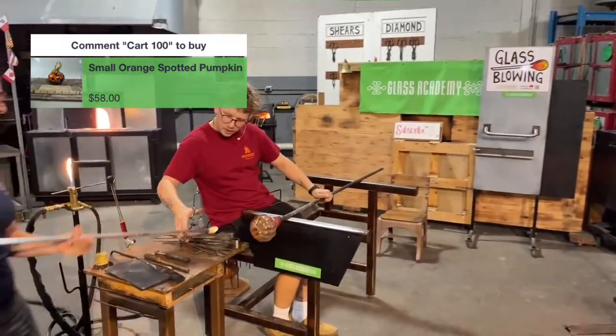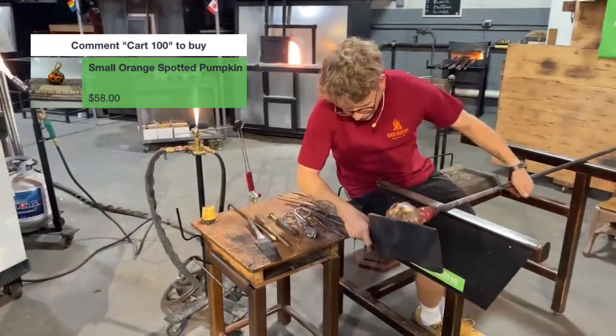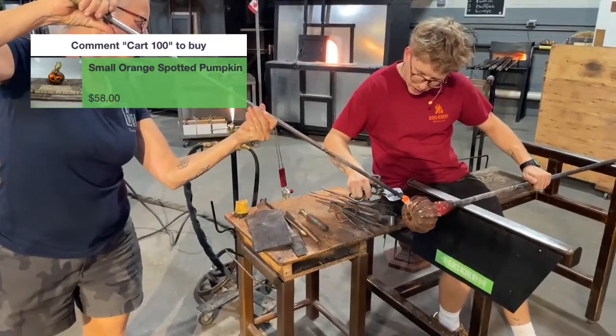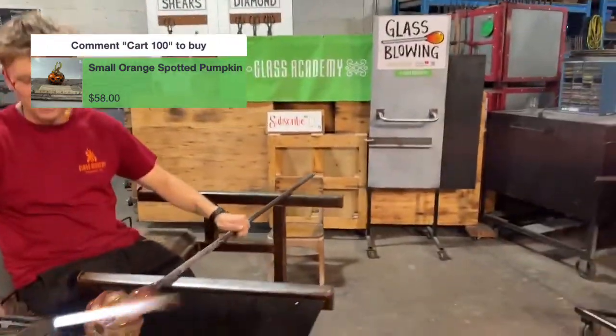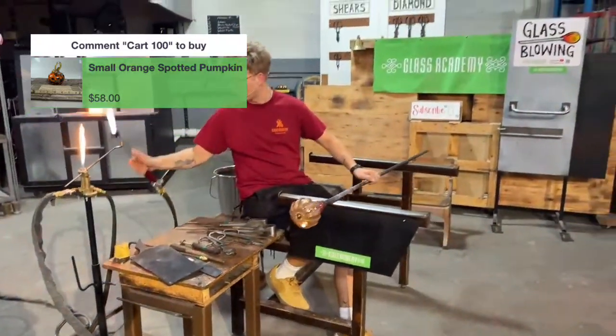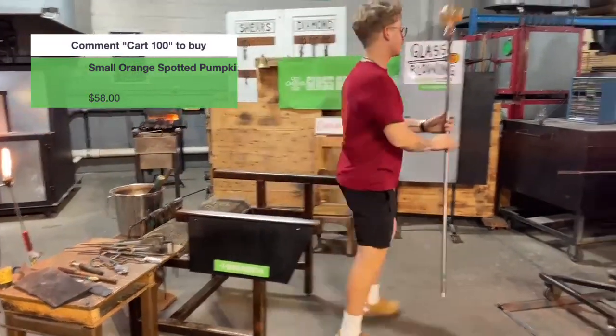Oh, did you need to flatten it? Starting to get a little bit of, yep. Would you like another bit right now? Ready. Starting to get a little bit of that purple metallic shine going on. That's telling me that the hole is a little bit gas heavy right now. It's iridizing before we're ready for the bling. So I'm going to go turn it down a hair, get it back to where it belongs, to then turn it back up to where it belongs.